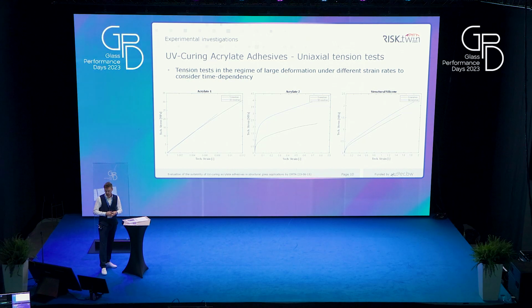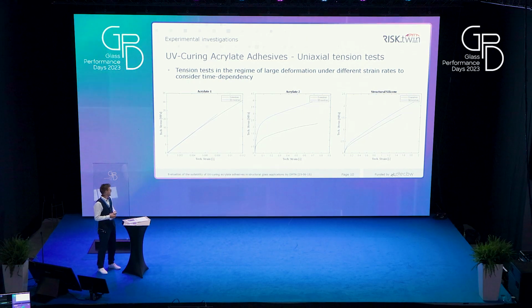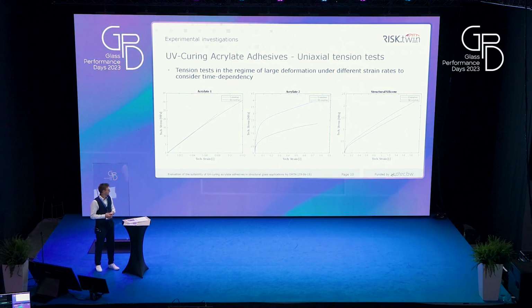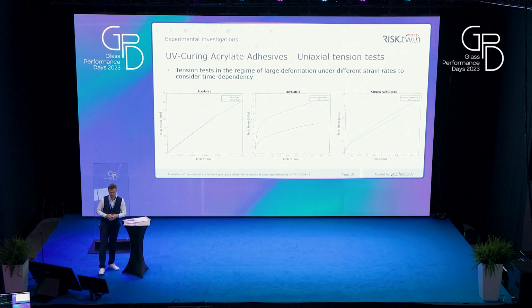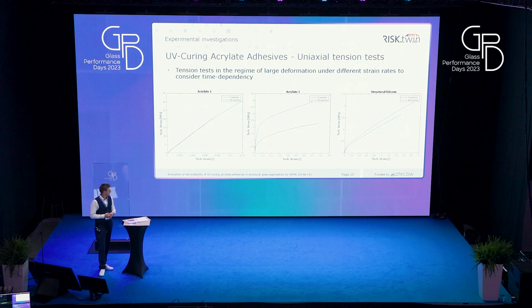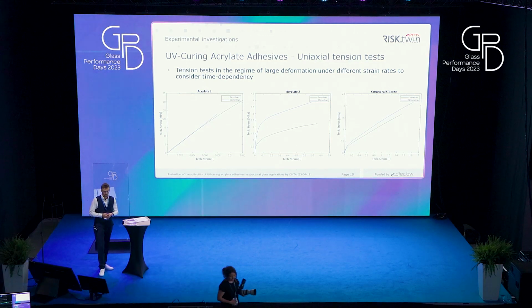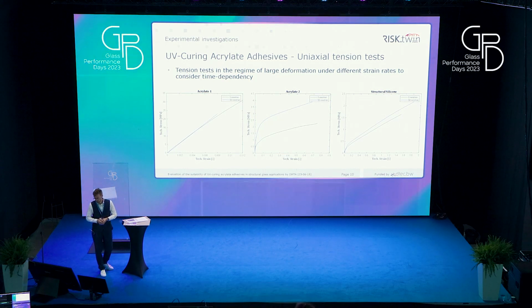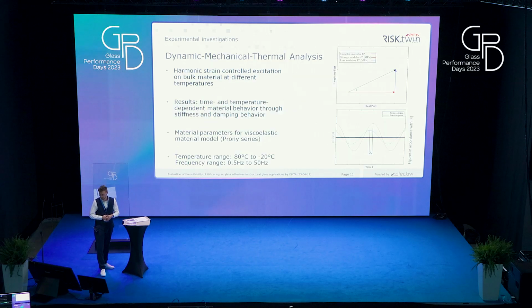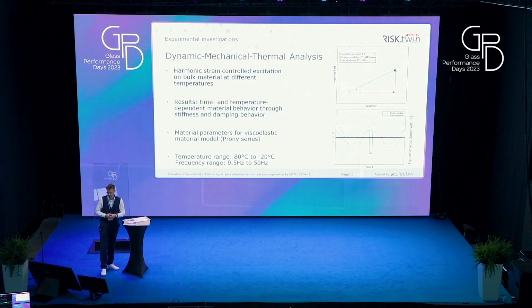And if we now compare the maximum stresses, acrylate 1 is nearly about 10 times higher than acrylate 2, but acrylate 2 still is about twice as high as the structural silicone. And as we can see, the material behavior of acrylate 2 is quite complex and some kind of viscoelastic. And to further investigate this, we performed dynamic mechanical analysis on this.